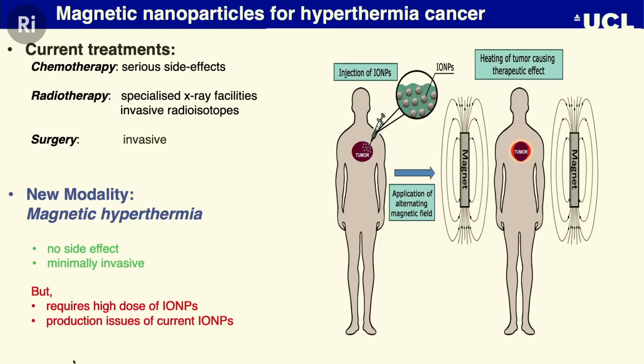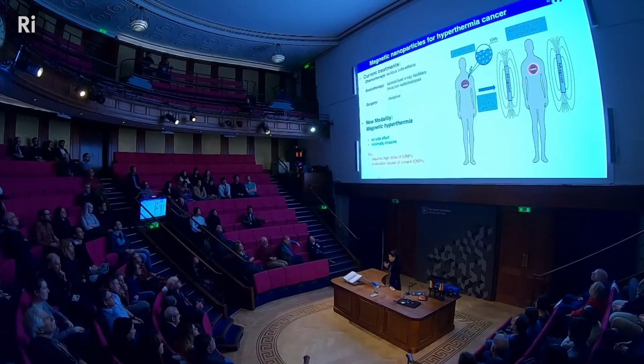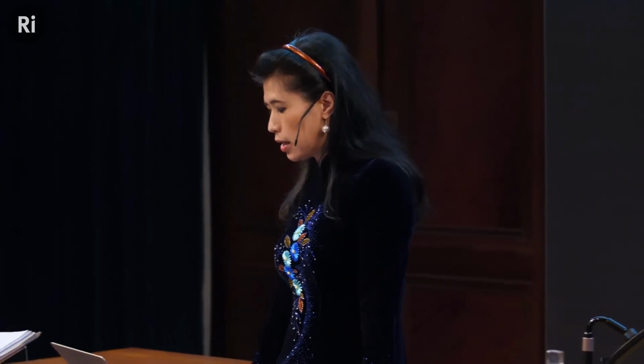So you take the magnetic nanoparticle, inject it directly into the tumor, and use an alternating magnetic field. The spin within the nanoparticle will follow the field, and the particle also possibly tumbles up and down, and you will have two effects. Not too scientific, but you have Brownian, because you know the Brownian experiment from high school, where the particles are tumbling up and down, and the Néel relaxation, and those two effects heat up the nanoparticles. When you heat up the nanoparticle, you kill the cancer cell locally, so you avoid side effects. And this is really, really exciting.